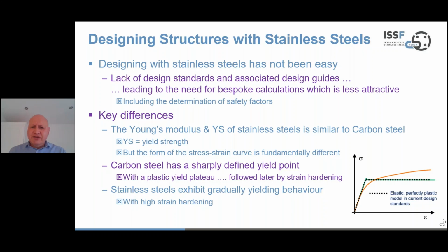So the Young's modulus and yield stress of stainless steels is very similar to that of carbon steel, but it's the form of the stress strain curve that is fundamentally different, and you can see the example of that in the bottom right hand corner of this screen. The dotted black and yellow line is the carbon steel line, and the curved orange line is stainless steel. So carbon steel has this sharply defined yield point with a plastic yielding plateau followed by strain hardening on the horizontal part of the chart, and stainless steels exhibit yielding behavior that is gradual with high strain hardening. So there is a difference, and we can use that to good effect.